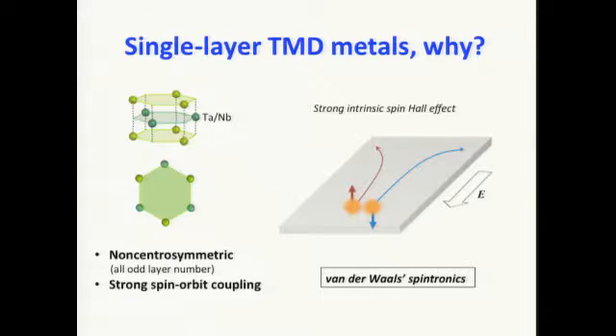And the second reason, which is more related to the physics I will talk about, is when you turn the material into a single layer, this is actually the structure of the material. If you look from top down, it's a honeycomb lattice structure, just like graphene, except that the two sublattice sites are now occupied by one transition metal atom and two chalcogen atoms. So you break the inversion symmetry of the material. You no longer have an inversion center at the center of the crystal of this honeycomb structure.